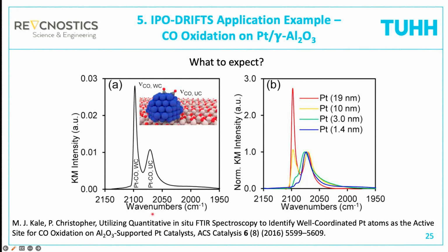Here is the reference given, and we can look and see what to expect. What you find is that you now have different CO molecules at the surface of the platinum nanoparticles. If the CO molecule binds to well-coordinated platinum sites that sit in a terrace, then you get the band here at around 2100 wave numbers. And if you have the CO molecule adsorbing on